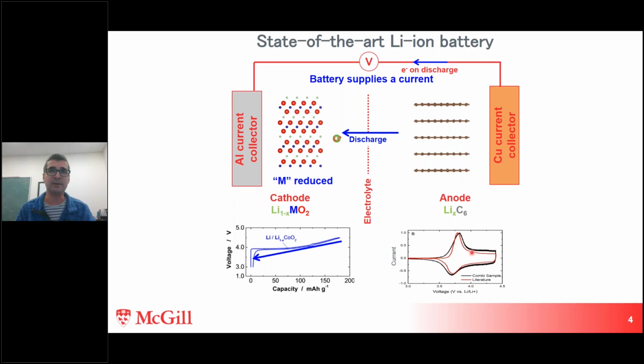So when we have a peak here, that corresponds to a plateau in the voltage curve. And where we had a difference in voltage here, it becomes a difference in the x-axis in the position of the peaks. So this peak is at a lower voltage than here. That difference corresponds to this difference between the plateaus. So we have very much the same information, it's just shown in a different form.